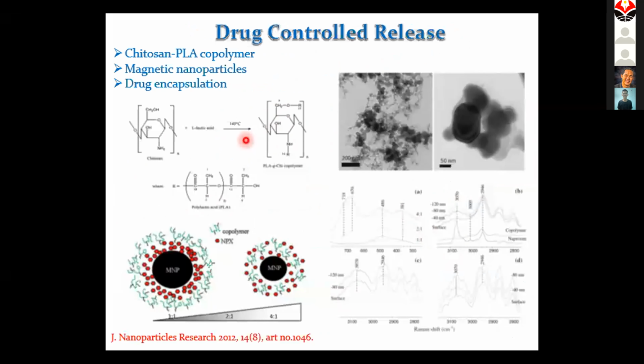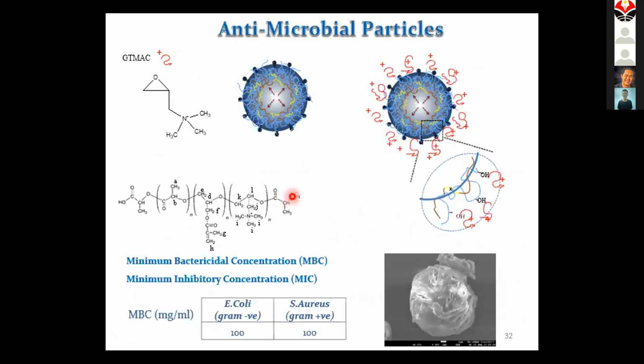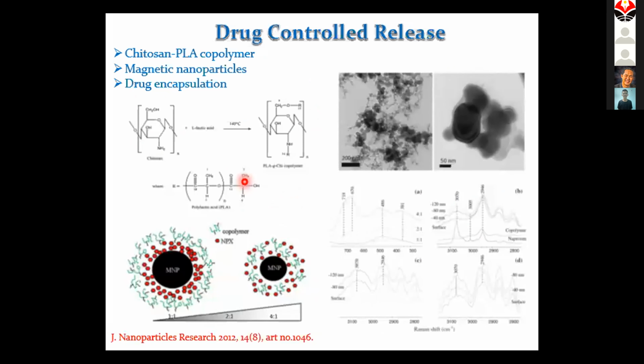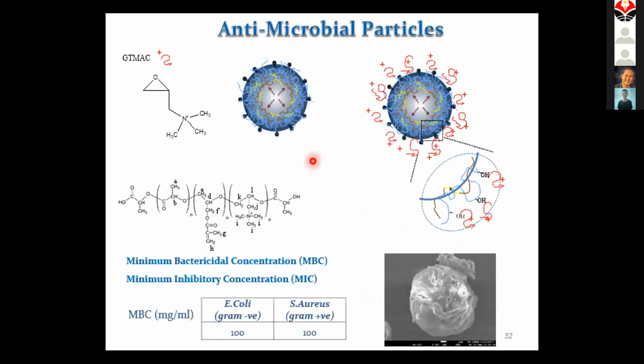Another example is making micro or nanoparticles from chitosan-co-PLA copolymer. We modify the structure of chitosan by grafting PLA onto it, then encapsulate drug inside, which also consists of magnetic nanoparticles. This can be used for drug controlled release applications.